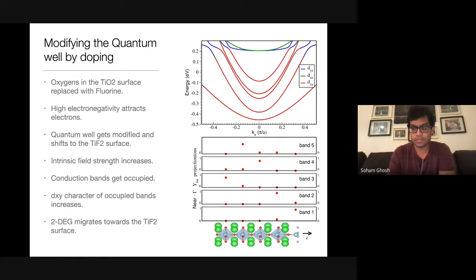So this fluorine sits on the surface. Why did I choose fluorine? The reason is that fluorine is extremely electronegative. And if it finds any electrons around, it attracts them towards itself. And the effect you can see on the electron levels is that they become much lower, and it draws all the excess electron bands towards itself. You can increase the field strength with this, and you can occupy more conduction bands with it. And you can bring the electron gas more towards the surface. And this is not just with fluorine. You can do it with anything.